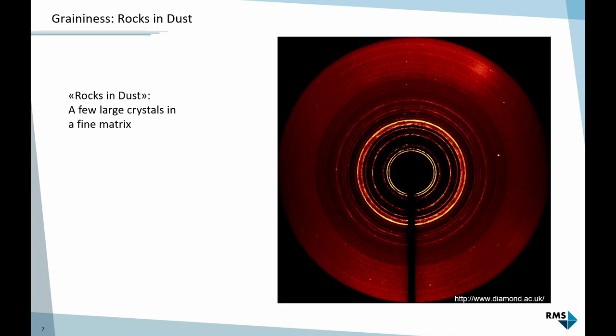A fairly extreme case is the so-called rocks in dust example. You can see a rather smooth powder diffraction pattern, the concentric rings, but we also see some spots. That might be just one large crystal in the sample that occasionally generates a diffraction spot. If we scan here and hit this spot, we would get a huge peak, probably more intense than the most intense powder peak. Out of nowhere. Then we re-prepare the sample and it's gone. This can be very misleading and cost a lot of time to realize it's just poor sample preparation.